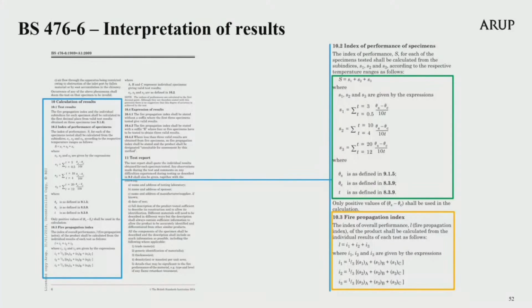Regarding the sub-indices S1, S2 and S3, I have provided the formulae to calculate them circled in the green box, which uses the measured temperatures shown on the screen now. These S values are then averaged and used to calculate little i1, 2 and 3, as shown in the orange box below. Sub-index little i1, sub-index little i2 and sub-index little i3 are then summed to obtain the index of overall performance I of the product. Please just remember that the only measurement taken as part of this test methodology is the temperature from the thermocouples within the chimney at the top of the combustion chamber at set time periods, which are then converted to temperatures.